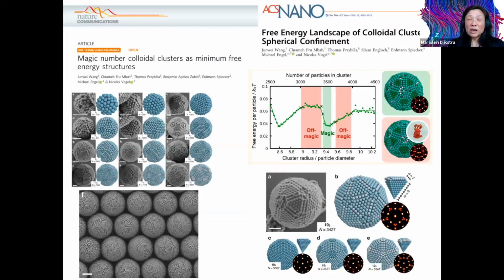More free energies were calculated by Michael Engel, who showed that there are really magic numbers. If you are at a magic number that fits perfectly inside the sphere, you find the free energy minimum. And they did beautiful work on calculating the free energies and looking at the structures of these icosahedral and rhombicosahedral clusters.